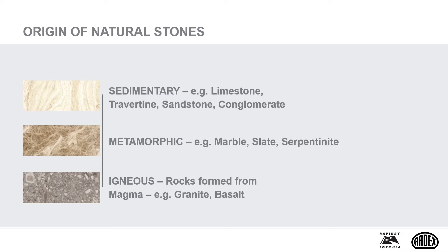Slate may be riven or unriven. Riven slate tends to vary in thickness and, as with all uncalibrated stone, the variety in thickness requires consideration for the installation and levelling products required. Some sources of slate may contain oil, which can lead to the initial adhesion being lost as the oil migrates to the tile-adhesive interface. It's always sensible to trial a small area first.